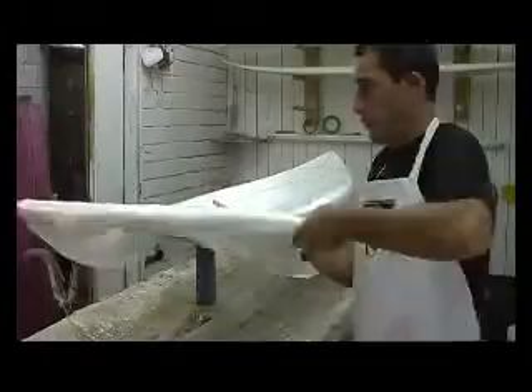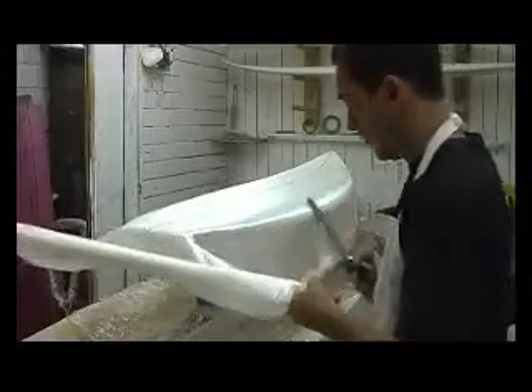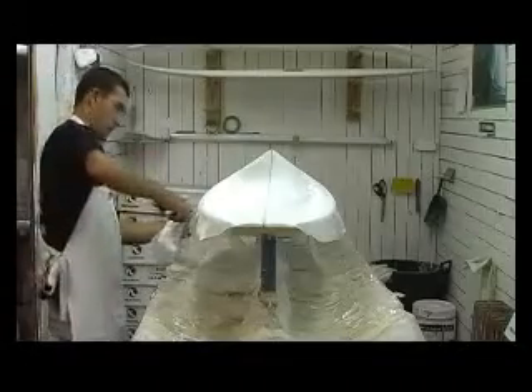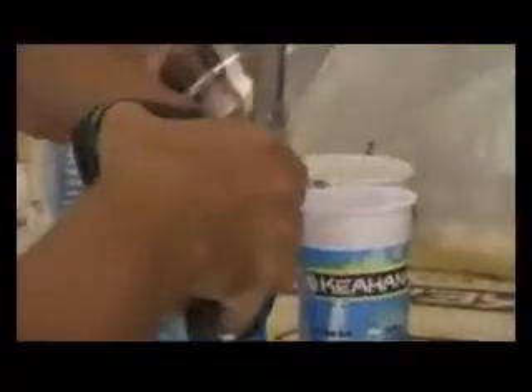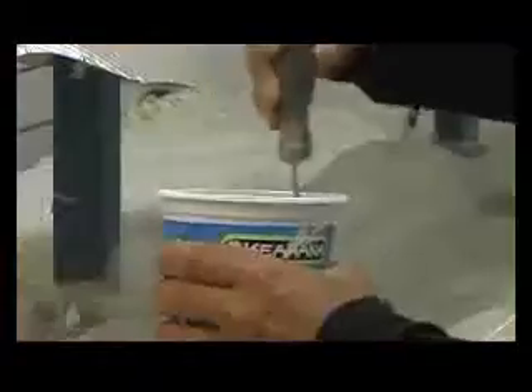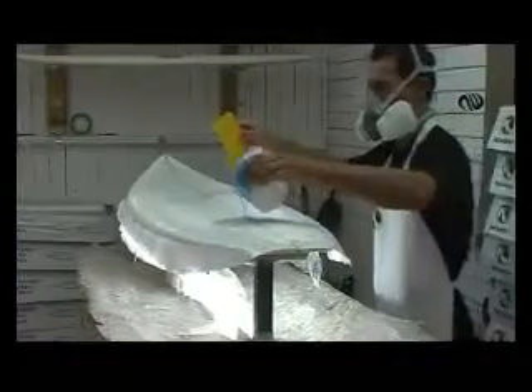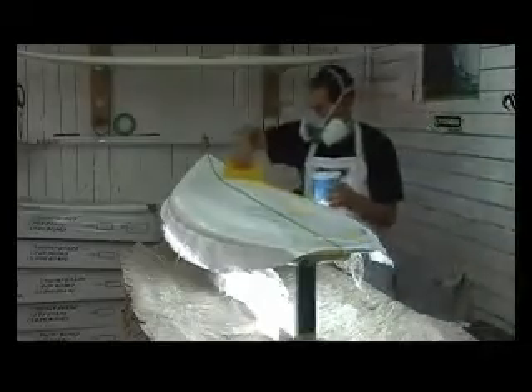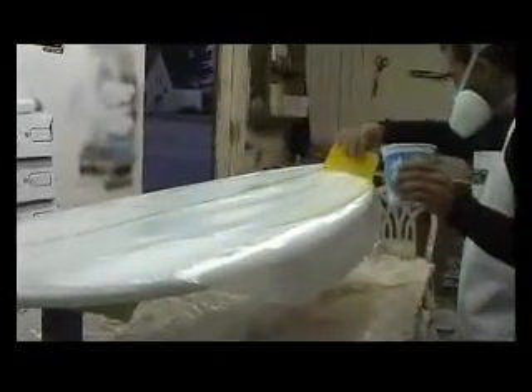Cut the first deck layer of KEAHANA cloth, allowing 1 inch of overlap around 2/3 of the board. It should not overlap around the nose area to give it extra flex. Glass this first layer using pot number 4A, glassing deck. Pour half of the resin over the board and spread it well with the spatula. With the remaining half of the resin, wet out the overlap, using a plastic shovel to help with this process.